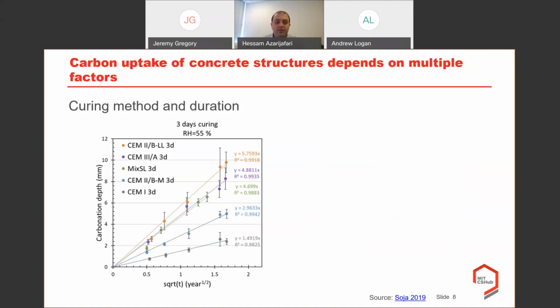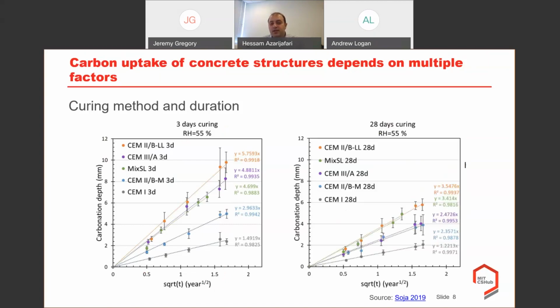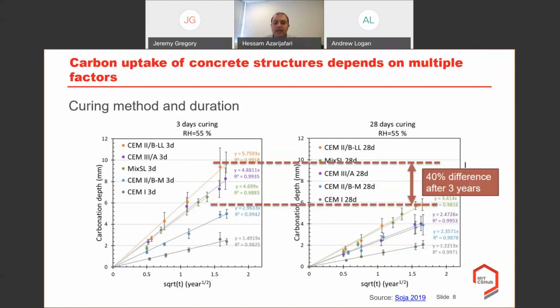And for different cement types, you can see different colors. For 3-day curing in a specific relative humidity, right? Once we increase this curing period from 3 days to 28 days, we can see that the carbonation depth will decrease significantly. Again, it gets back to the permeability of the concrete, analogous to what we observe for the water to binder ratio. And we can see up to a 40% difference after 3 years for the carbonation depth once we are increasing the curing from 3 days to 28 days.